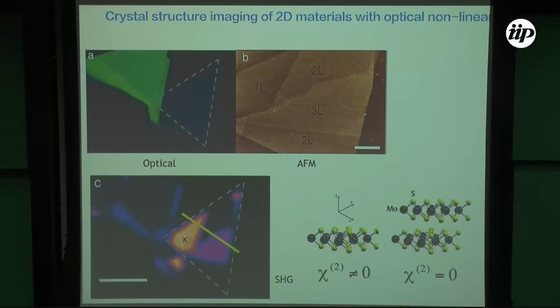Okay, and this is the second harmonic image of this same flake. Here in high intensity is the second harmonic emission of the sample. We see a very strong second harmonic from the monolayer. In the bilayer we don't see any second harmonic. In the 3 layer we see some second harmonic with a smaller intensity than the monolayer. And here in the bilayer again there is no second harmonic emission.